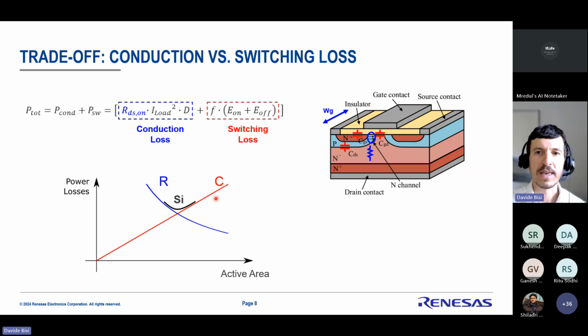In fact, if you take a conventional transistor, like here we have a vertical silicon device, and we try to reduce the resistance, we need to make the active area bigger. By making the active area bigger, we can reduce the resistance. But as the area increases, the capacitance increases too, and so the switching losses now are going to increase. So you can see that there's an optimum minimum, below which we cannot go. A certain active area will just give us the minimum of conduction and switching losses for silicon.